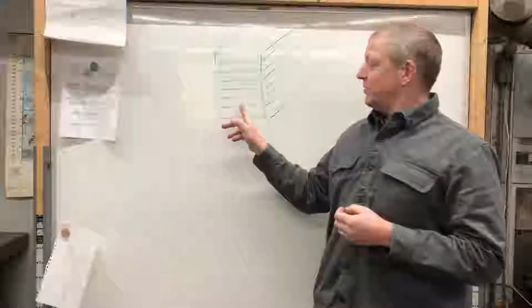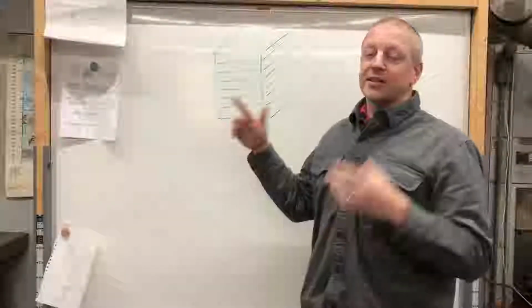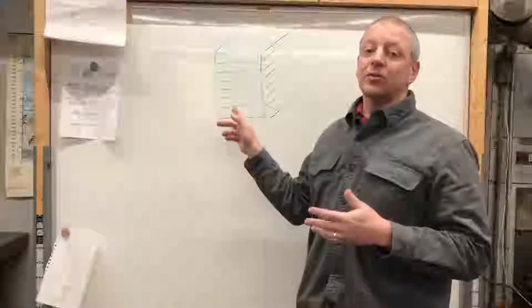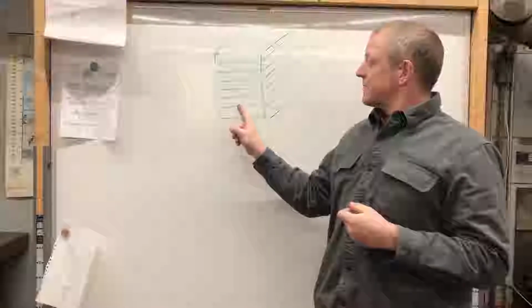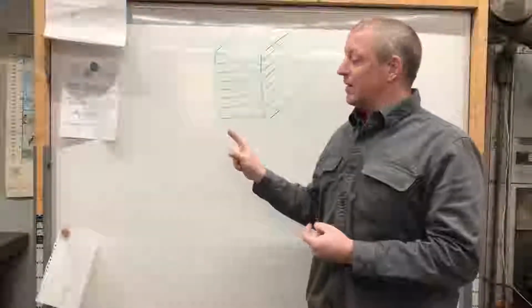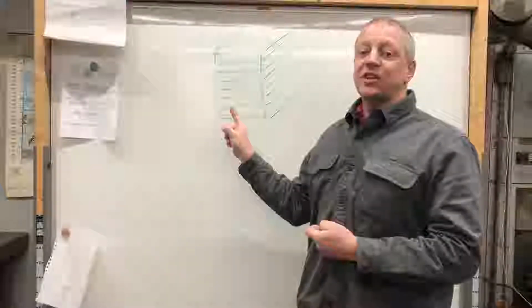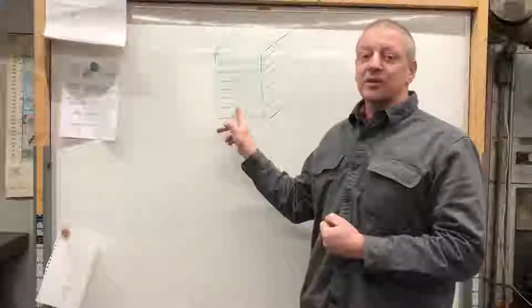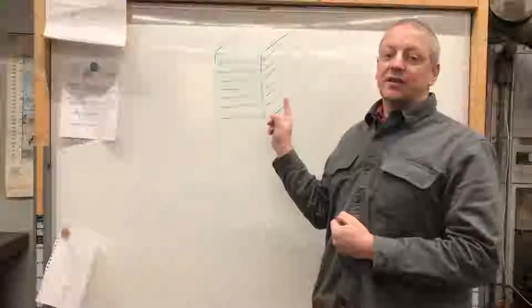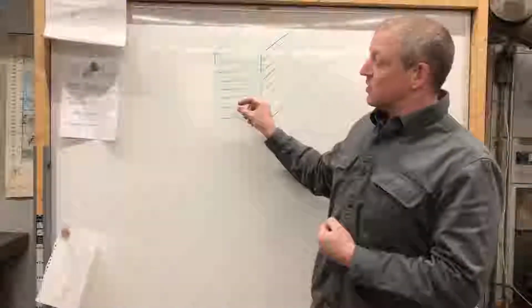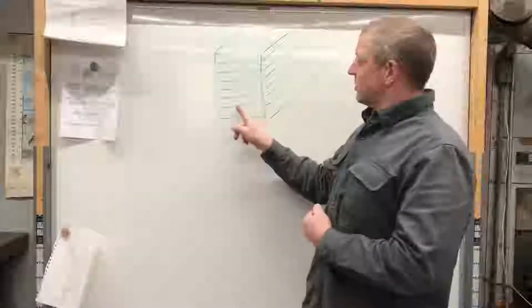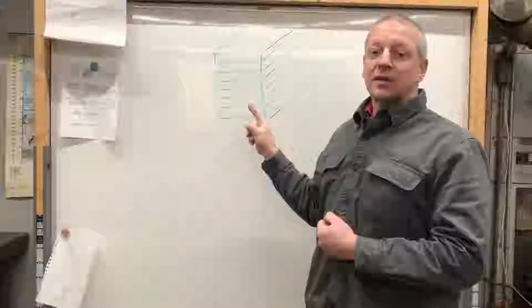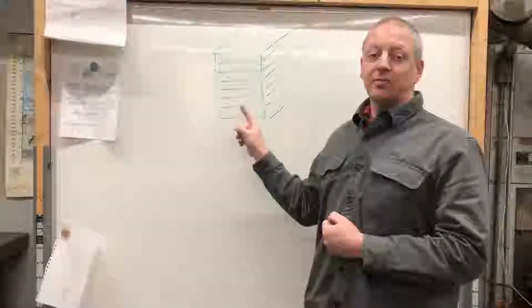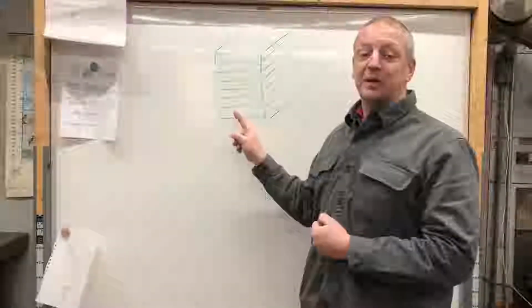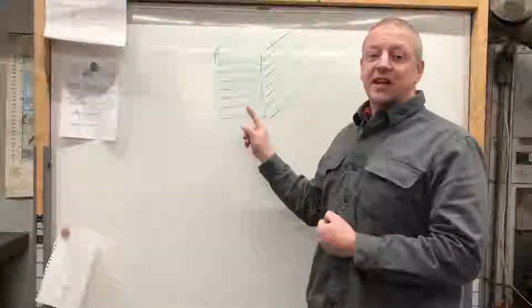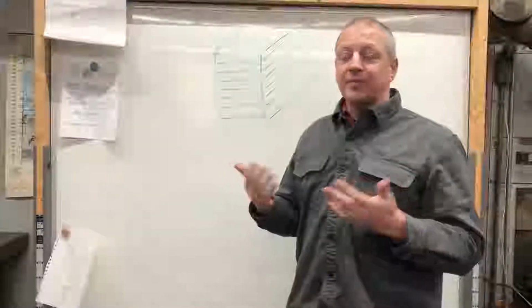He pointed out that if you take your atom of flux, not that you can have an atom of flux, but your molecule of flux, your little particle of flux in here, when you smash these layers together, it is in fact physically impossible for a particle in the center to be ejected. The amount of distance that is being closed to squeeze it out versus the amount of distance it has to travel, it becomes a physical impossibility. Your little particle of flux would have to exceed the speed of light. It basically accelerates to infinity, and that's impossible.